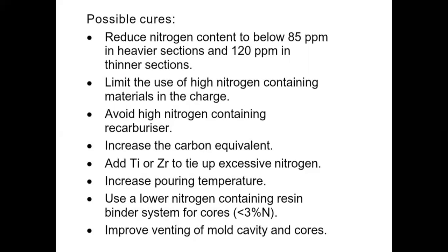Increase the use of low nitrogen-containing resin binders for the core. Nitrogen in resin should be less than 3%. Improve venting of mold cavities and cores so that gas can escape easily.